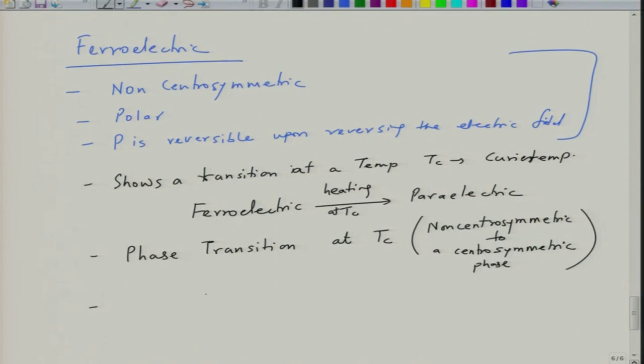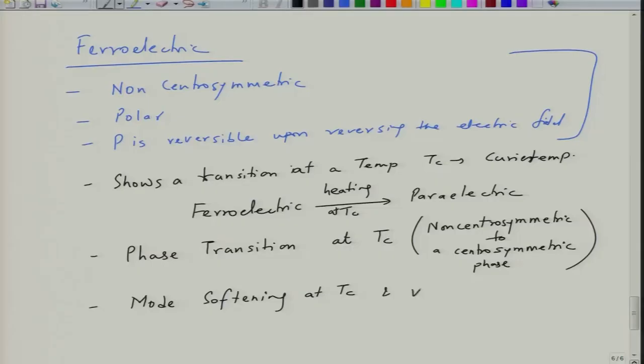And then in physics language, we also call it a mode softening at TC. And the soft mode vanishes at TC. That is, when you do Raman measurement on these materials, you will see a disappearance of the soft mode at TC, and this is a signature of ferroelectric, the vanishing of the soft mode at TC. Okay, these are certain characteristics of ferroelectric material.